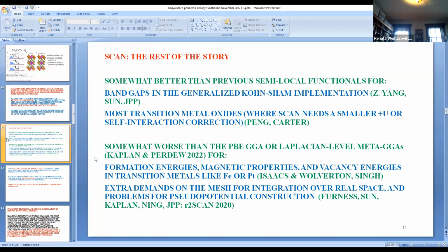if you look, for instance, at the formation energies of intermetallic compounds, the magnetic properties of solid transition metals, or vacancy formation energies of transition metals like iron or platinum, it turns out that SCAN is actually less accurate than GGAs and Laplacian level meta-GGAs. And we interpret that in the following way.